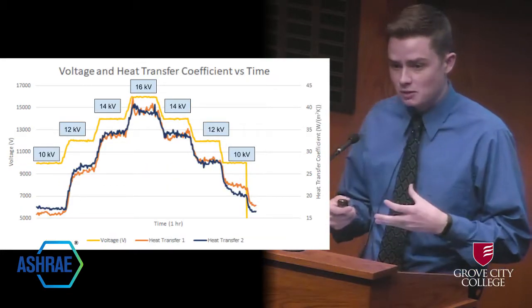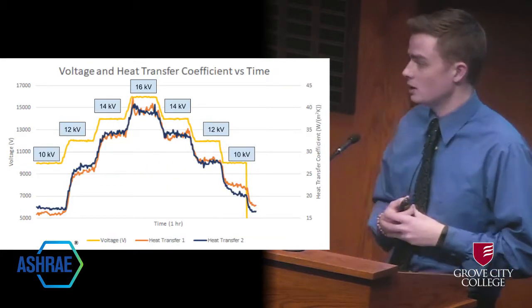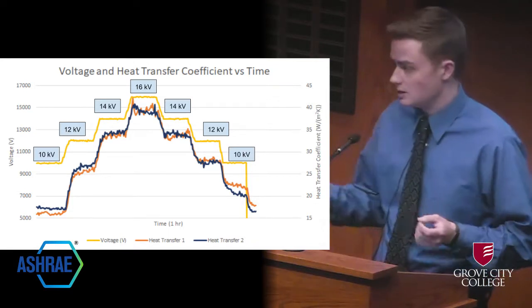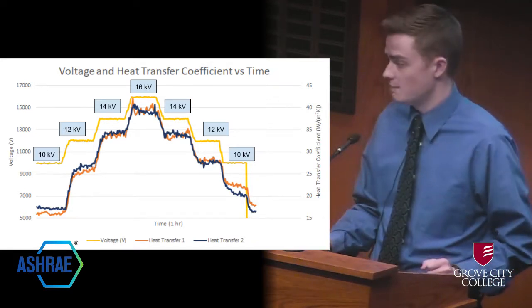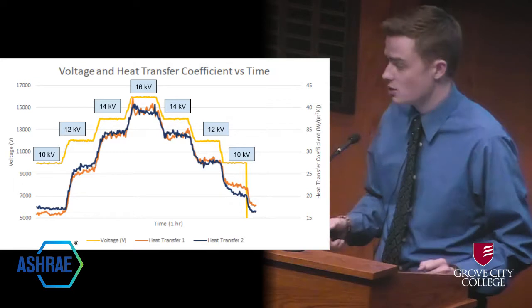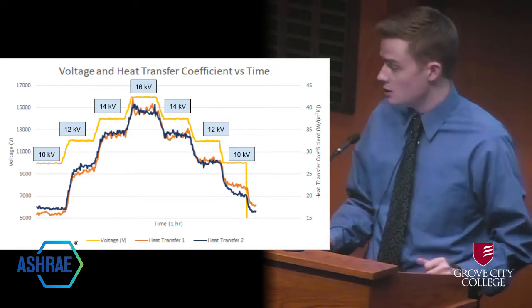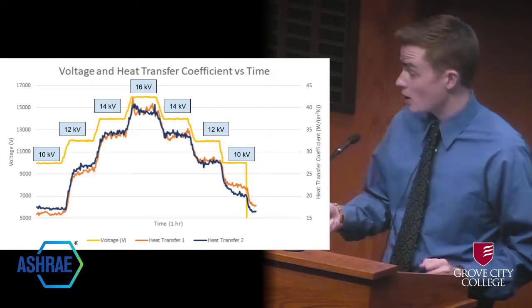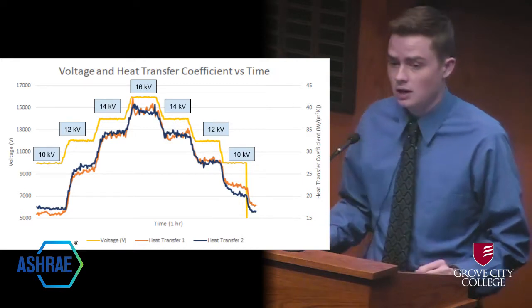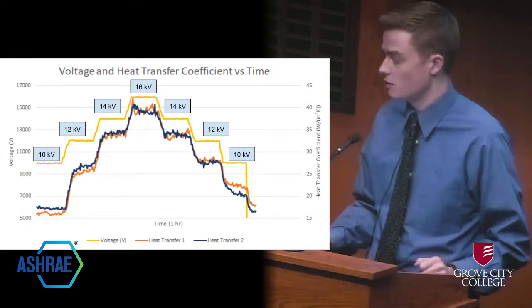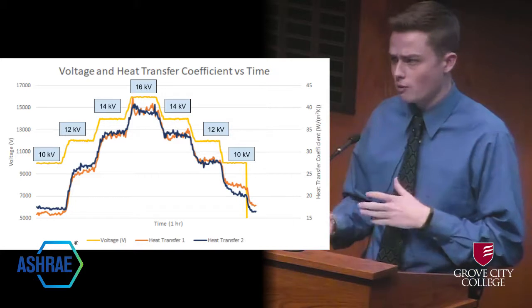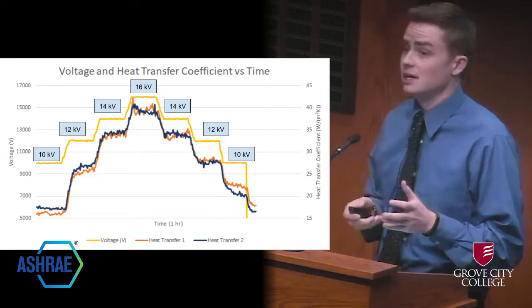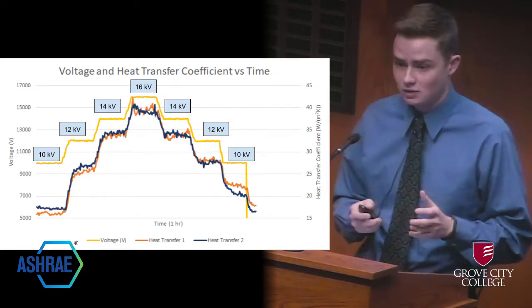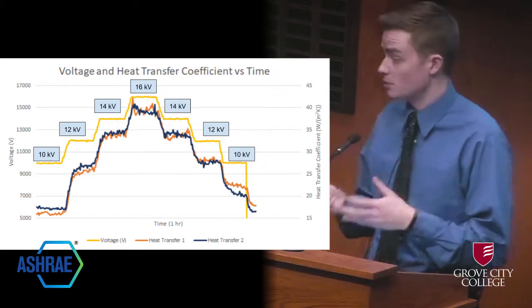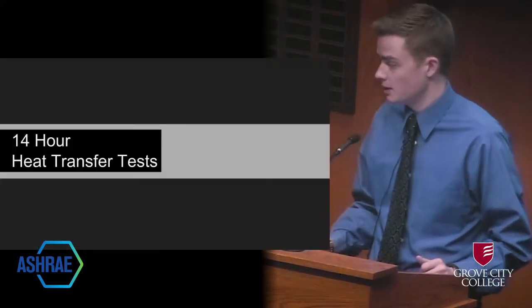Here's kind of the same thing, but this is for the heat transfer coefficient. Again, the yellow bar is the voltage over time, and then the orange and blue lines are the heat transfer coefficient. So one thing to note, it went all the way up to around 40 for the heat transfer coefficient. And another thing to note about these results is that it's symmetrical around the 16 kilovolts. So that is cool because we're getting consistent results.